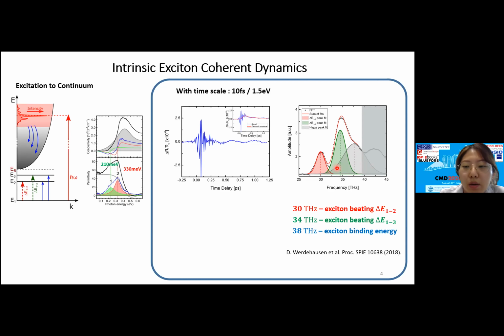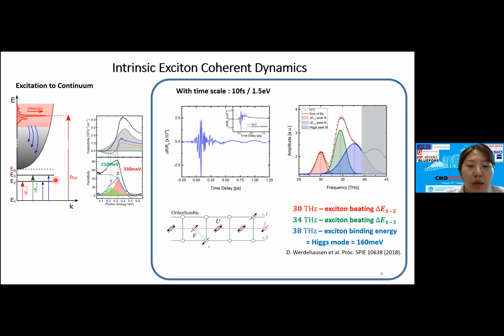So therefore, we can call this a Higgs equivalent mode. But these modes and this extrinsic level's intrinsic excitonic binding energy show us this system is like a Rydberg series, and this indicates a Wannier-type, 3D Wannier-type exciton state. But we know structurally there is a charge transfer exciton in our tantalum nickel selenide. So what makes our excitonic coherence length longer?